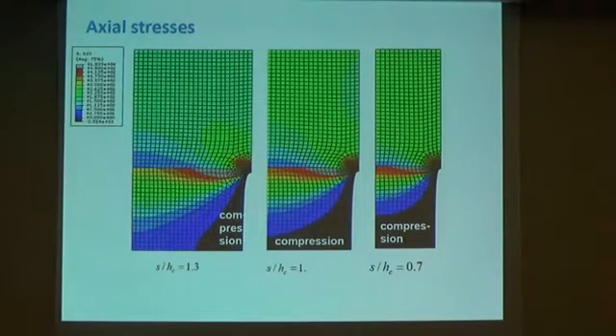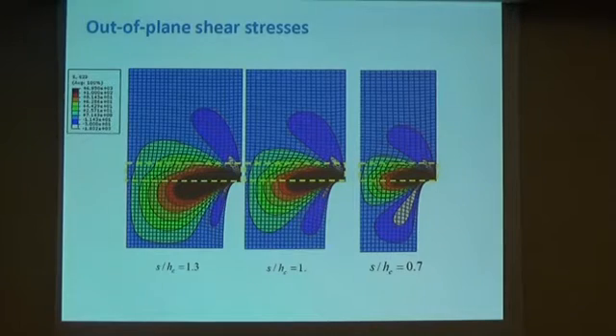Finite element analysis allowed us to see the emergence of this compression region next to the crack surface, and as crack spacing becomes smaller, this compression region grows in size. As you see, for smaller crack spacing, it covers the whole length of the representative segment, meaning that new cracks cannot appear here because of the compressive stresses. So when we look at out-of-plane shear stresses, we can investigate further this shear layer assumption that we made and establish more accurately the width of that shear layer.